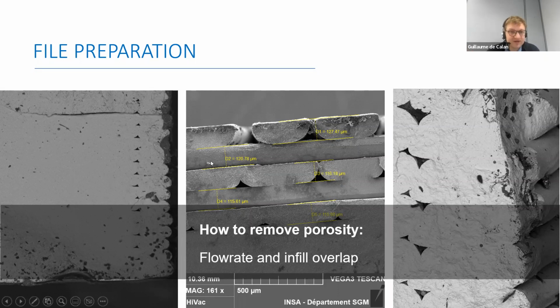And you may also have defects which are only on one zone of the print, which is typically what you can see here. The rest of the print is relatively dense. You do have a crack here, which is probably linked to that porosity, and you have nice aligned porosities here, which are between the shell that we printed first and the infill. This again can be corrected by another parameter, which is called infill overlap, which basically says how much the infill needs to go over the shell so that the connection is fully dense. And so you need to increase that from maybe 20% up to 50, 60, 70%, depending on the prints and how dense you need your part to be.